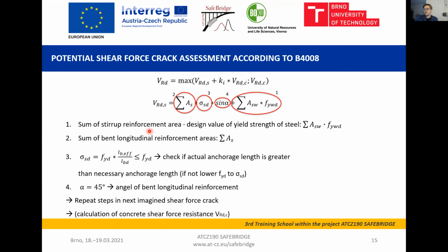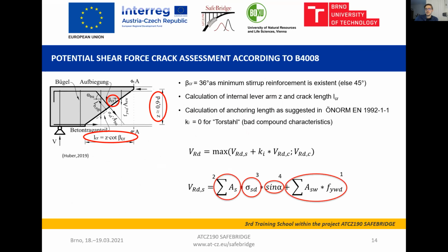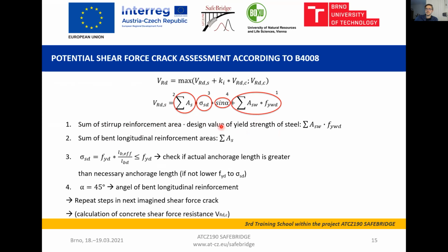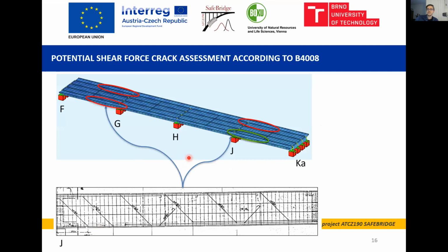First, you have this potential shear crack shown in the slide before. You take the sum of the stirrup reinforcement and multiply it with the design value of the yield strength of the steel. Then you take the sum of the bent longitudinal reinforcement and multiply it with sigma SD, and you have to check if the actual anchorage length of the reinforcement is greater than the necessary length or not. If not, you have to lower the value. Then all these steps have to be repeated for the next potential shear crack. For this bridge, it was done in the first field around bearing G, and because the bridge is symmetrical, it's the same at bearing J.